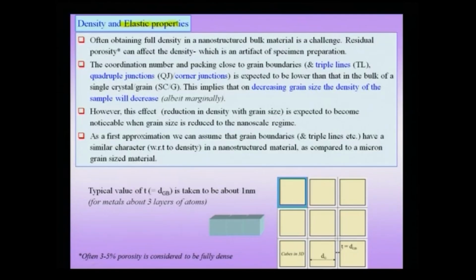Now, suppose I am taking a bulk material, then the fraction of grain boundaries in such a material and the fraction of what you might call triple lines is very small, and therefore, we can ignore them in terms of the overall contribution to the elastic properties. Of course, we cannot ignore grain boundaries when we are talking about plastic properties, and we will take up those important contributions later, but as far as elastic properties go, we can often ignore the grain boundary contribution.